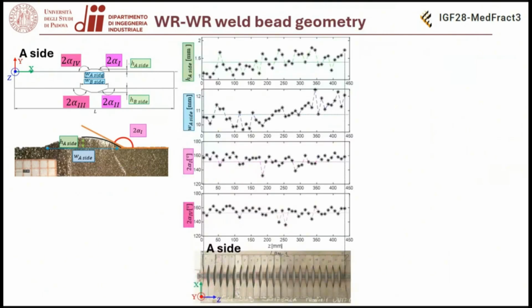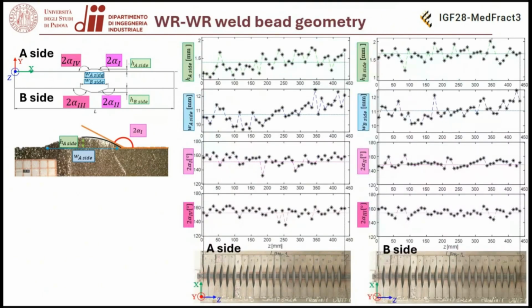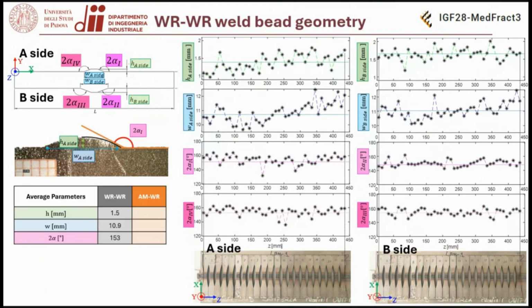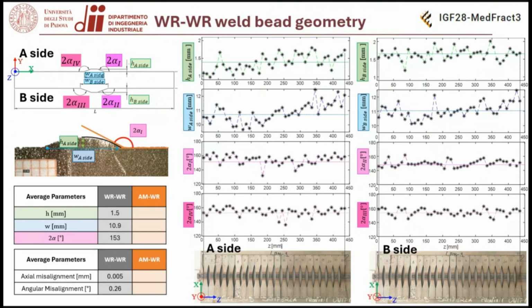We also carried out an extensive geometrical analysis, focusing specifically on the weld bead by measuring all the main parameters, that means the opening angle, the height, and the width of the weld bead, both for the top side of the specimen and also for the bottom side of the specimen. And here you can see the mean values that we acquire. We also analyze the misalignment of our specimens, and as you can see in this case, they are negligible.